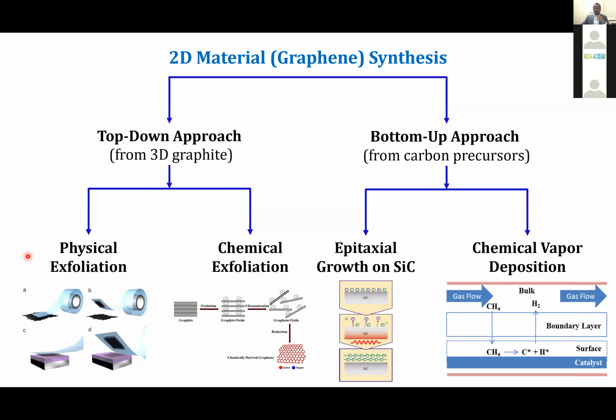And this is the approach where the Nobel laureates that I showed you were the first to exfoliate graphene from graphite in 2004. They were able to measure the electrical conductivity in the graphene, and that led to the Nobel Prize. However, the graphene produced on silicon oxide is very small. Though it is of good quality, it's the highest quality, in fact, the size is very small. It may not be applicable for any large scale applications that an industry might need.